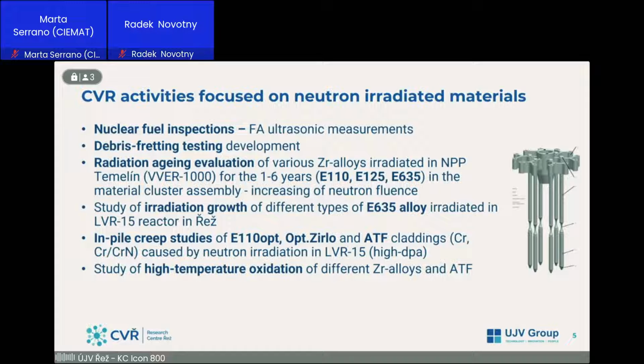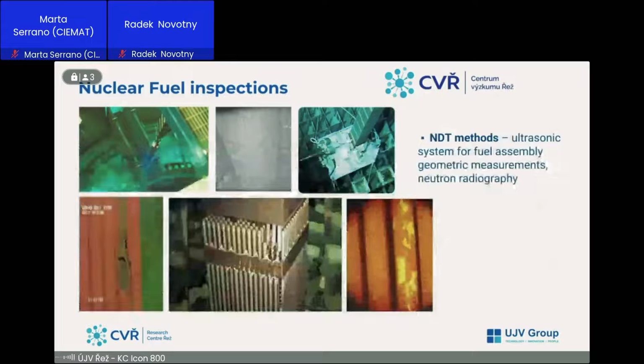Then we study irradiation growth of different types of E635 alloys. It's a Russian alloy which is irradiated in the LVR-15 reactor in Řež. And we study the in-pile creep of E110, optimized ZIRLO, and as well ATF claddings, which are based on chromium and chromium nitride coating. These materials are also irradiated in LVR-15. And another huge area of the study of zirconium alloys is high temperature oxidation of different zirconium alloys and ATFs, in cooperation with the UJP Institute in Prague.